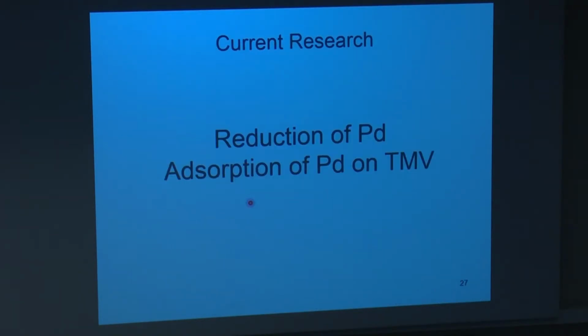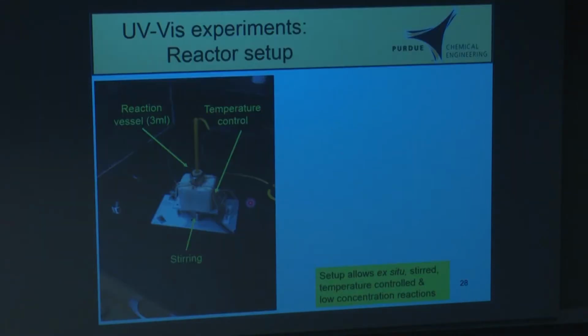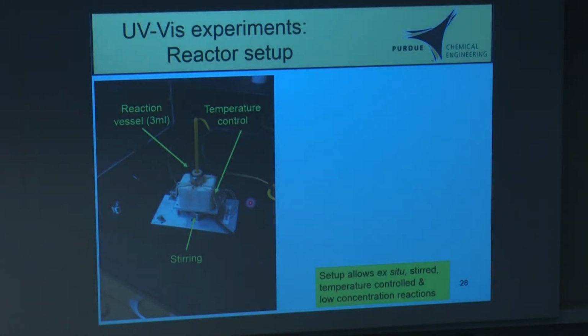But we still don't understand this whole palladium reduction, and we collaborated with Jeff Miller because he was doing X-ray absorption spectroscopy, so we could actually look at the reduction kinetics of the palladium ion. And we also use UV-Vis experiments, because we have a UV-Vis instrument here, and it's not that expensive to use.